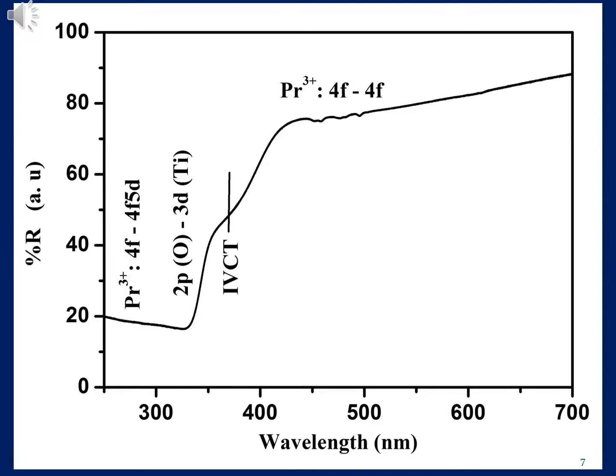Now, experimentally, can we observe this charge transfer state? Yes. The diffuse reflectance of our sample shows an absorption corresponding to electrons excited from valence to conduction band in a region below 330 nanometers. And below that is a broad band corresponding to the gap. Within the gap, corresponding to the IVCT, in a region of 360 nanometers. So yes, experimentally, we can observe the IVCT state.